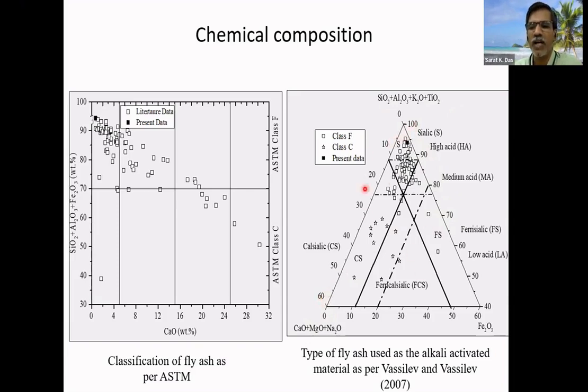And what I have done, I have put around 50-60 fly ash data points from all around the world. If you see, most of the fly ash is sialic, mostly dominated by aluminosilicate compounds. There are also some fly ash which we call high calcium fly ash. They are also called calcialic, because the calcium compound is not very high, less than around 30%. If you compare another industrial waste, blast furnace slag, the calcium content is more than 35%. So in that comparison, this high calcium fly ash contains calcium oxide varying from 15 to 30%.